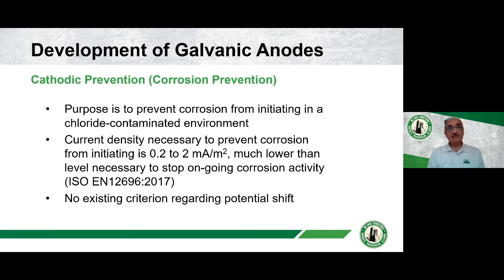Looking at standards that were available, the only thing that we could find for preventing corrosion was EN 12696, ISO 12696, where it states that to have an effective cathodic prevention current, you need to be in the range between 0.2 and 2 milliamps per meter squared. There was no other criteria, for example, about shifting of potential. So this was basically the standard that we were looking at.